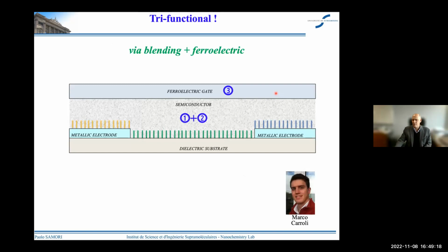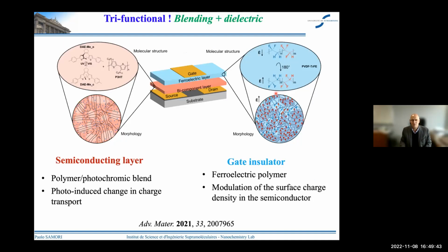And here again, you have to identify a new interface in your device and come up with a new function. And that was the use of the blend of the P3HT with the dielectric, and here we interface this with the third functionality, which is a ferroelectric gate insulator. The organic ferroelectric insulating material that we have chosen is pretty well known. It's here on the right, this